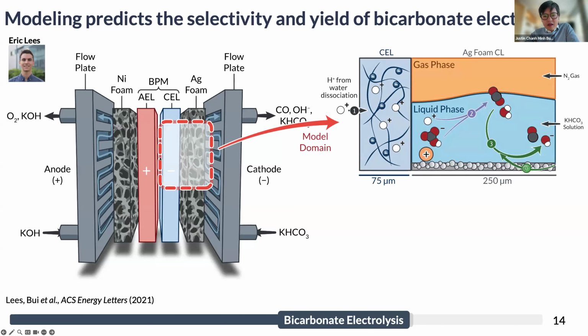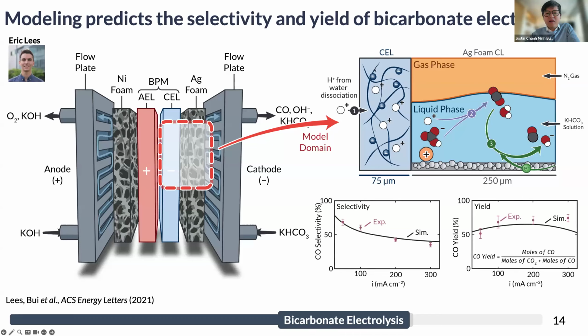And so, you can see here, you can zoom into this, and this is the modeling domain that we chose, which was, we were really only interested in this system in the dynamics between what's happening in the cation exchange layer where our CO2 is being desorbed and what's happening within that porous electrode where our reaction is happening. And with this simplified model of the membrane and the porous electrode, we can actually get really good agreement between what's happening, again, in our model, in our simulation, and what happens in the experiment.